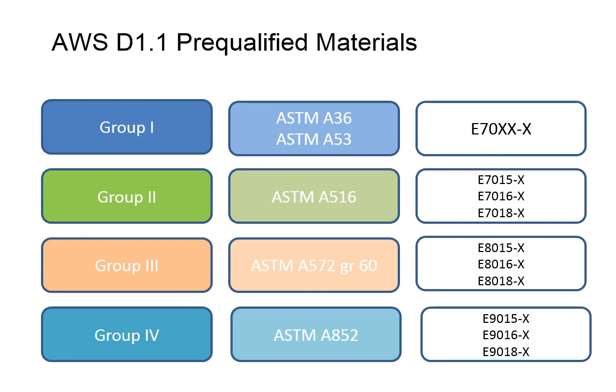Well, by the time you get to group 3, you're dealing with something like an ASTM A572 grade 60. So in those, you have your base metals, and your filler metals for those base metals come off the chart in clause 3. All of this is in clause 3, which is like a chapter, of AWS D1.1. So in there, you've got the 80 KSI materials. Well, like I said before, anytime I see an 80 KSI for a filler material, I know we're dealing with something that is a little more delicate. I don't know if delicate's the word, but you have to handle it with a little more care. You need to make sure that your preheats are right and you're not cooling it too quickly when you're done welding on it, and that you're generally following the rules.